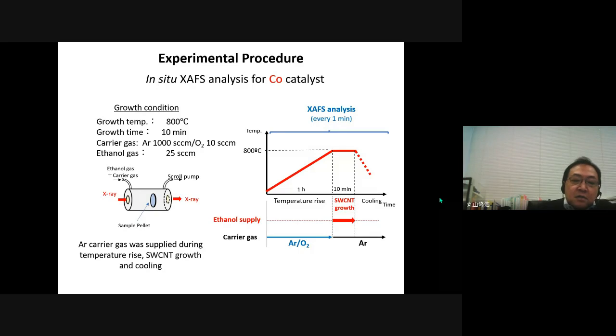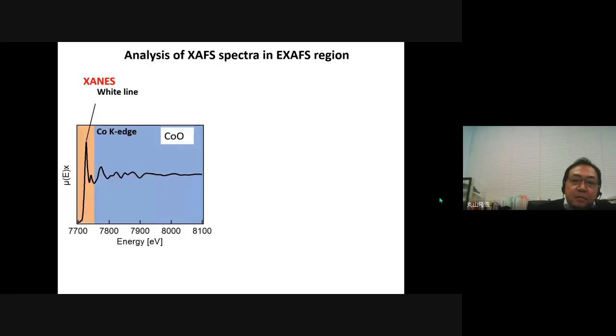This shows temperature sequence. The growth temperature was 800 degrees C. After the furnace temperature reached 800 degrees C, ethanol gas was supplied to grow carbon nanotubes. So after in situ XAFS measurement, we analyzed EXAFS spectra in the EXAFS region.